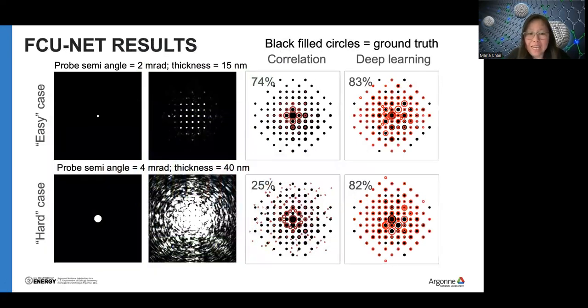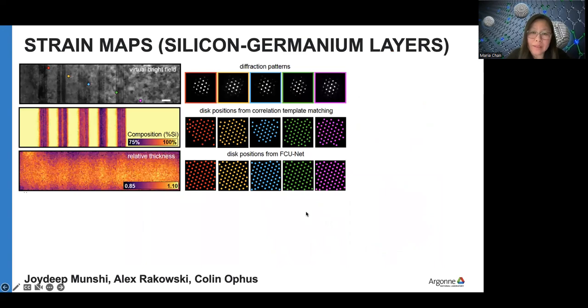On the top is an easy case where the CBED image almost looked like a diffraction pattern you would recognize. You can draw, with some intensity thresholds, the Bragg positions. In fact, a previous approach, which is called correlation, can do that. Using deep learning with the FC-UNet, we improve the accuracy by a bit. But the remarkable cases come in something like this, where there's no chance for a human to pick out the Bragg positions. And in fact, the correlation approach has completely failed, but the FC-UNet still does a reasonable job. So that was what we published recently.